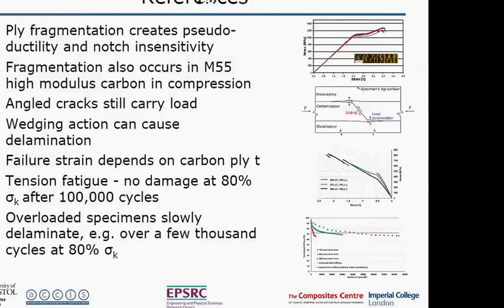Just one last question for me before I hand it back: have you analysed what would be the optimal thickness of that interlayer to maximise your pseudo-ductility? For example, would it be just a single layer of fibres, or is it something thicker than that? So for the sorts of materials we've been looking at this morning, we take the carbon-glass, this one here has about 0.06 millimeters, so about 2-3 plies. For this particular configuration, that's about the optimum. But it depends on the fracture toughness. So if you have a much tougher matrix, then you can get away with thicker plies.